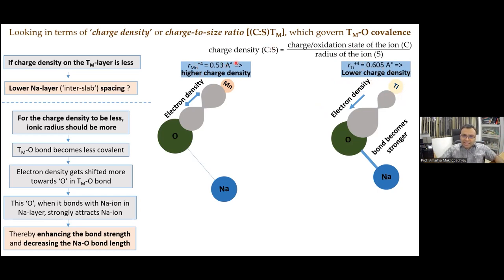So the overall charge density of a transition metal ion is smaller because the radius of the ion is larger, and vice versa. So having a lower charge density, by having a lower charge to size ratio, when I say size here, I mean the ionic radius, I can render this transition metal oxygen bond less covalent, which means